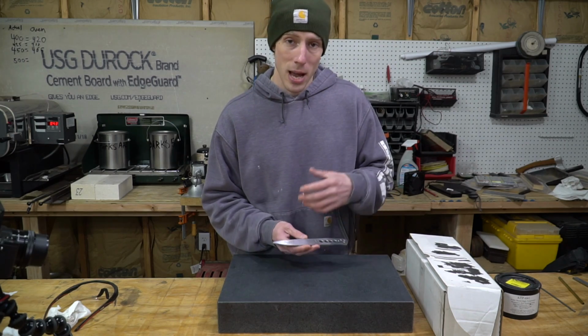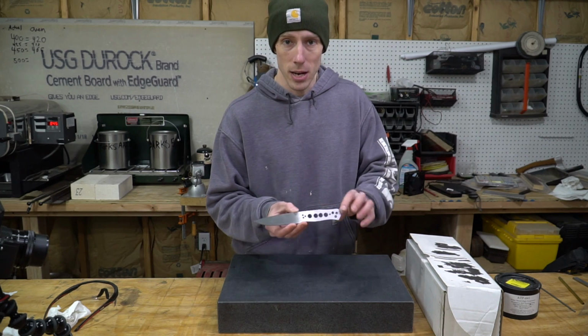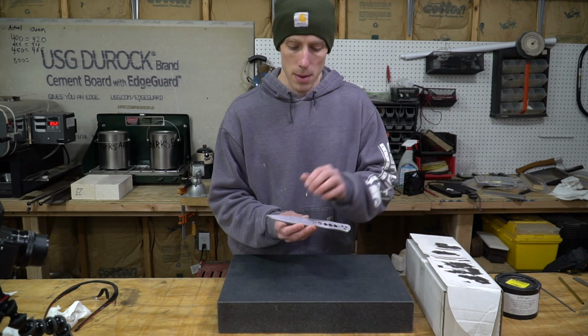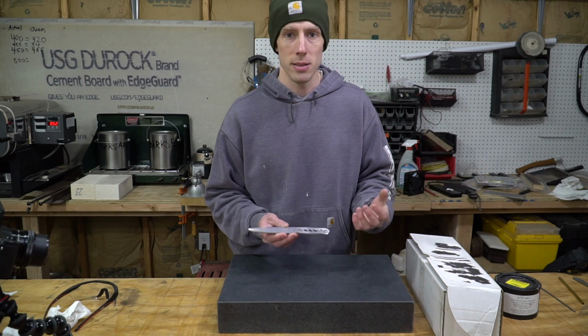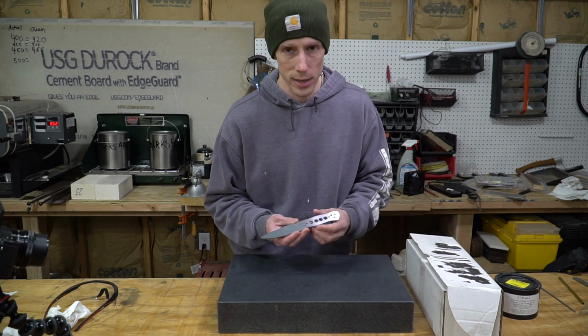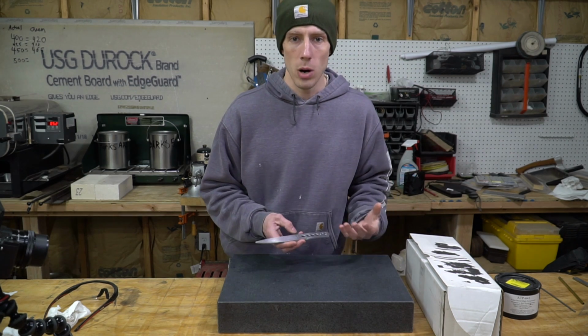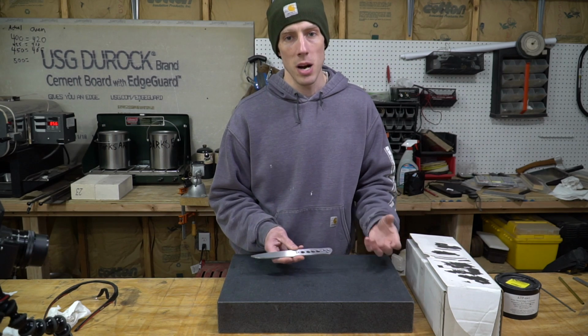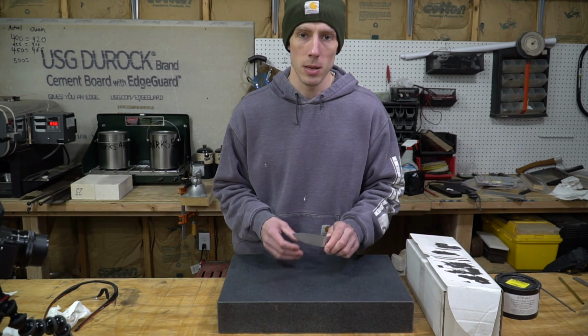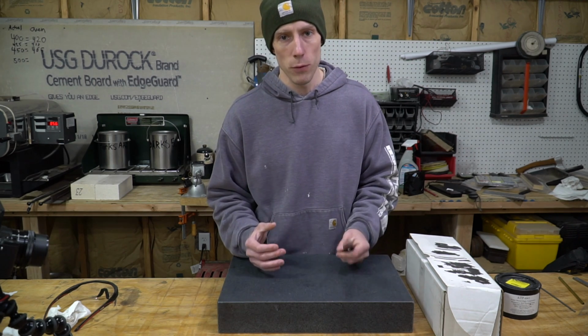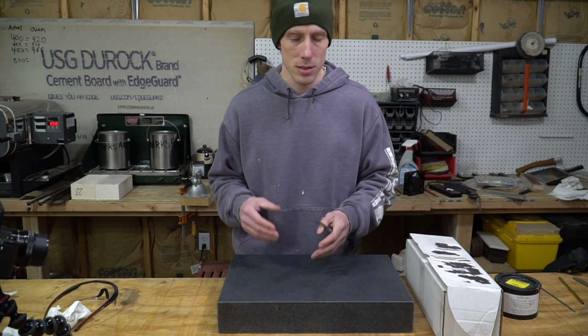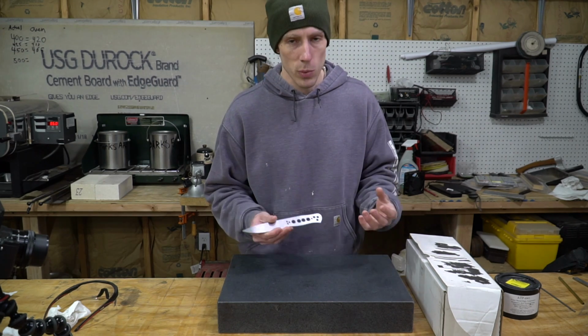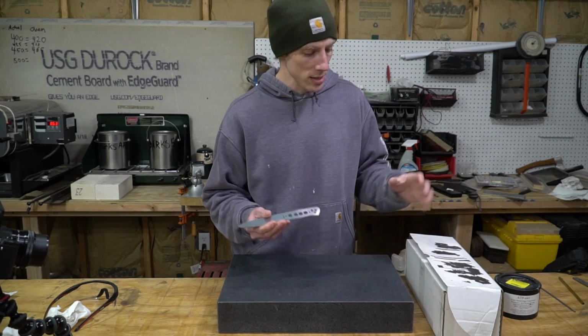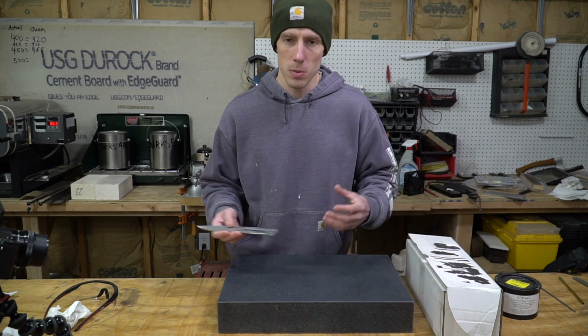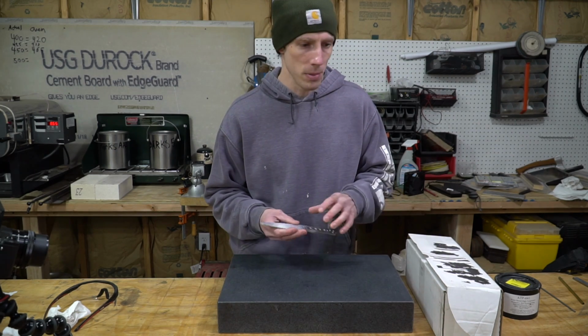Now later on we're going to have to remove the scale to make the knife shiny again, and the less decarb that happens on the surface, the less decarb we have to remove later on. So this foil packet will help prevent as much decarb as possible during the thermocycling process. Now if you're doing this in a forge, you cannot do this process. This is only if you have an oven, but don't sweat it. This is not an absolute necessity. This just helps the finishing process later on and helps speed things up, in my opinion.